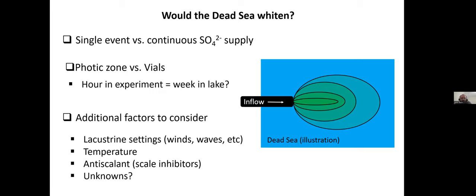Another thing is just the matter of scale. The photic zone in the lake where crystals in suspension can contribute to a whitening event is about 9 meters, whereas the vials of the experiment are several centimeters. So if we correlate the times for the crystals to clear from solution, an hour or so in an experiment would equal a week or longer in the lake.